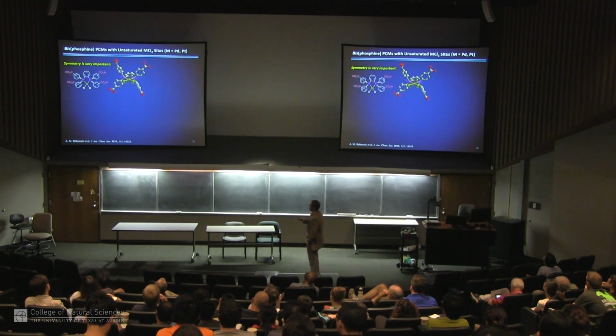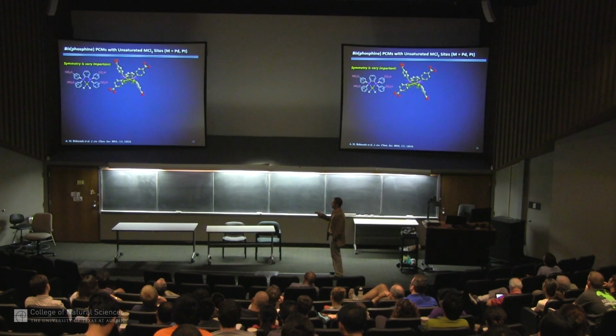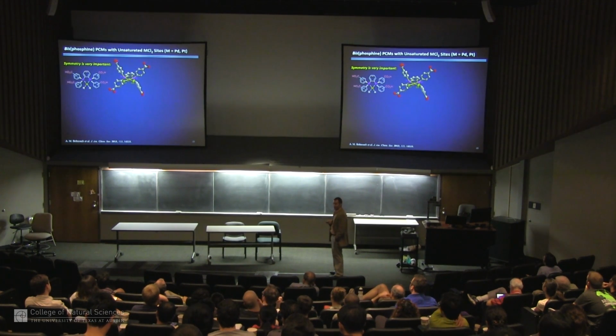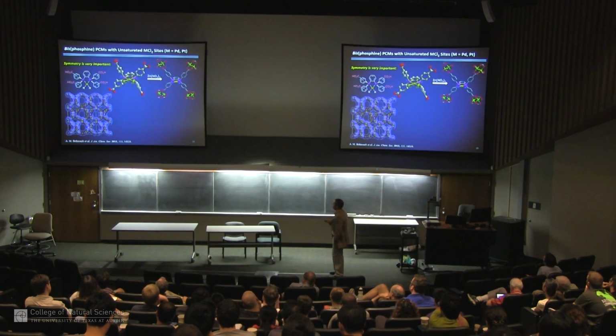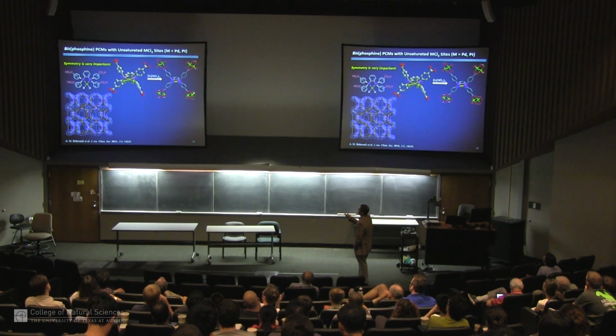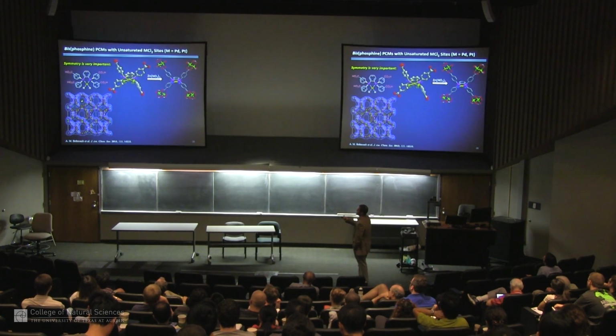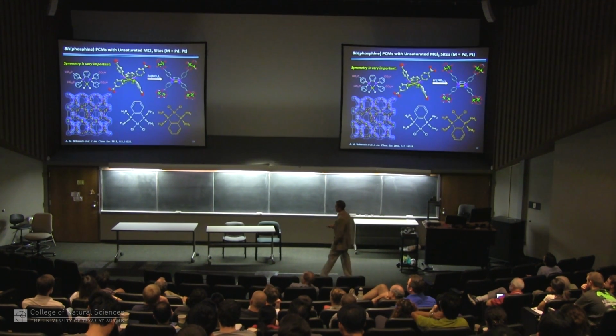And so Alicia took the ligand, reacted it under conditions that suited the formation of crystals, and I'm not belittling this chemistry. We do have to make grams and grams of this often to find the right conditions to make a framework. And it becomes, unfortunately at this point, a little bit shotgun. But if you get the conditions right, you can react your species with metals that will polymerize these acid groups, make these incredibly high symmetry species, and we get this really ordered porous material with large oval pores, and in every wall you can see one of these catalytic sites.